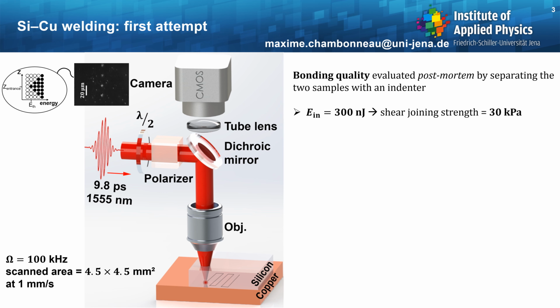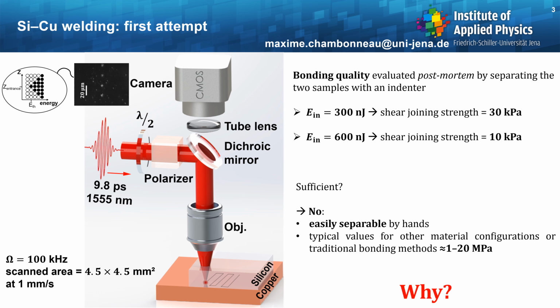So if we try that and fix the input pulse energy to 300 nanojoules, then the shear joining strength is 30 kilopascal. Okay, and then what if we double the input pulse energy and go to 600 nanojoules? Then the shear joining strength is 10 kilopascal. That's weird. But the main question is: is that sufficient? And sadly, the answer is no. I mean, the samples are easily separable by hand with those shear joining strengths, and the typical values for other material configurations or traditional bonding methods are on the order of 1 to 20 megapascal. So how can we explain this?